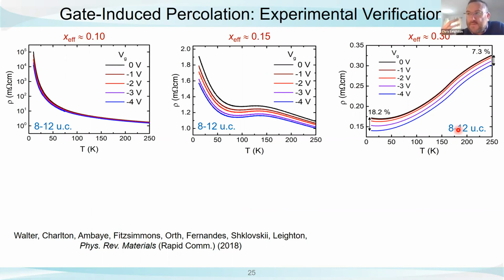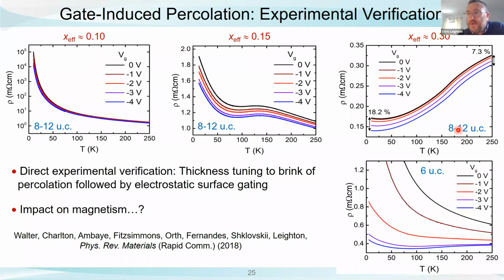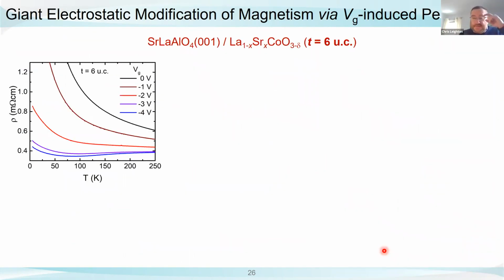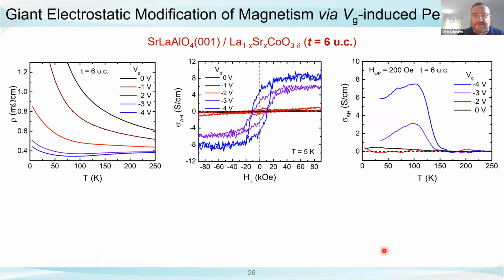We decreased the thickness from 8 to 7 to 6 to 5 unit cells. And it turns out at 6 unit cells and below, we get exactly what was predicted. So we go into an insulating non-ferromagnetic state. And then as we apply -1, -2, -3, -4 volts, we can drive it through a percolative insulator-metal transition. And of course, the interesting thing here is, does ferromagnetism come along with this? So we tested that again using the anomalous Hall effect. This is at 5 Kelvin. We're applying voltages now through -4 volts.